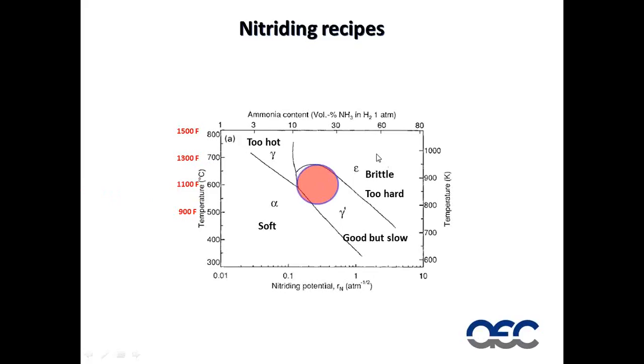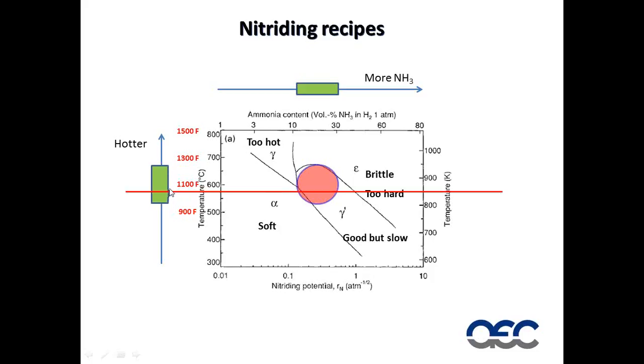So we have this red circle. This is our optimum range that we want to work in. And if we look at it in terms of the ammonia content or the nitriding potential content here, we have a green range to operate in. And if we look at temperatures, we have a green range to operate in. I'm now adding in a line, which is the tempering temperature of H13. If we start to go above this, we start to soften our dies. Not dramatically at first, but over many, many nitriding cycles, it could become an issue.